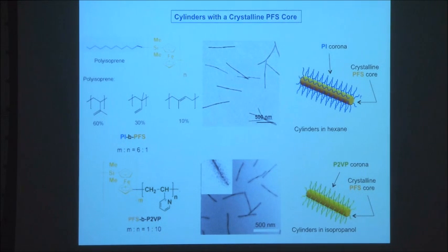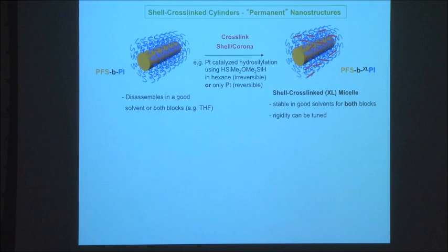So these structures are stable in the selective solvent, and if you remove the solvent, they're still stable. This is electron microscopy under vacuum, so these are still stable structures. They don't disintegrate when you remove the solvent. But of course, if you add a solvent that's good for both blocks, these will re-dissolve and go back to individual unimers. But you can actually make these structures permanently stable by introducing cross-linking into the shell of the structure.